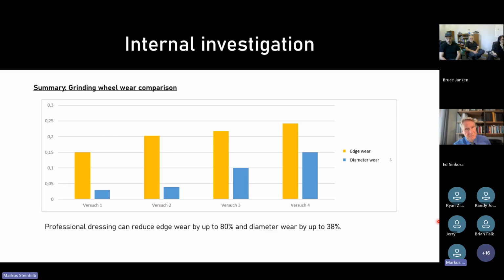And in this graph, we can see the edge and the diameter wear of the grinding wheels. The blue one is the diameter wear, and the yellow one is the edge wear of the grinding wheel. And you have to imagine that on the first 3 tests, we already did 20 workpieces, and on the last one, we just did 2 workpieces. And you see how much diameter and edge wear we have after only 2 workpieces. The grinding edge wear is reduced by up to 80% only because of dressing and sharpening, and the diameter wear increased by 38% during the whole tests. This shows that proper dressing can greatly improve the wheel's lifetime.